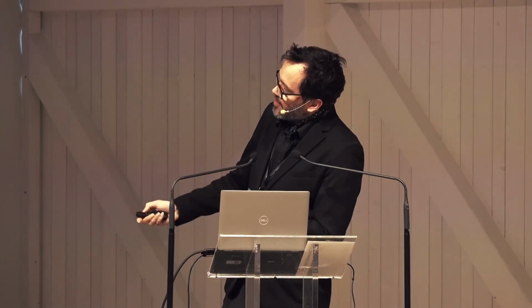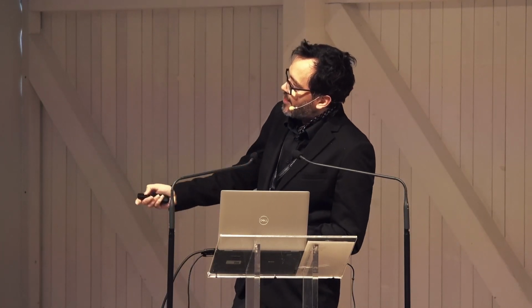And then we measure the porosity, and we collect experimental data where we were reporting, for different formulations, I mean different weight percentages of active material in the slurry, the porosity as a function of the viscosity for different solid contents, okay? You see here a very messy cloud of points, right? We collected something like 80 conditions here, okay? It's not large. Each experiment was repeated 5 times, okay? It's high quality. Machines produce high quality electrodes, very reproducible electrodes. You have very small errors, right?